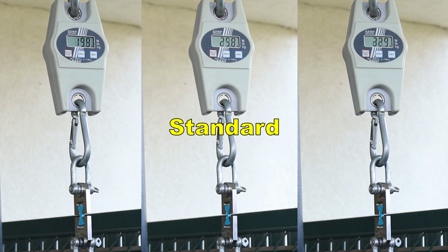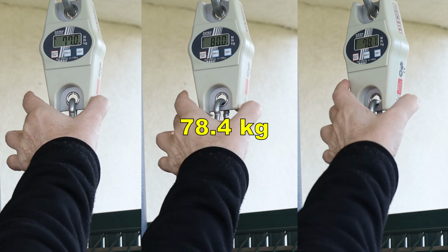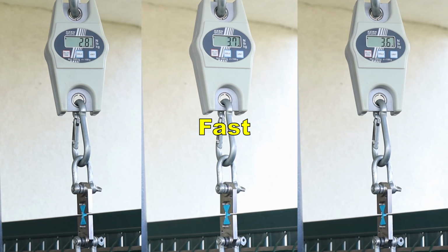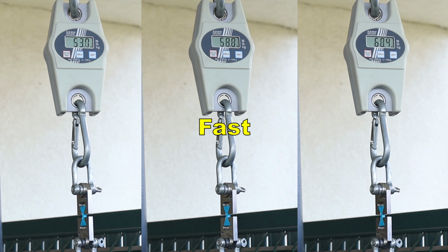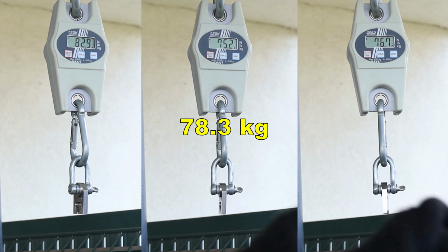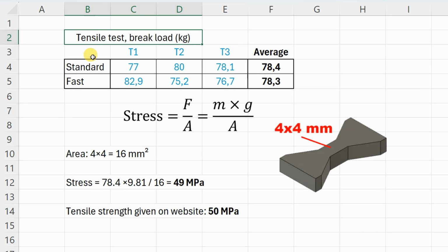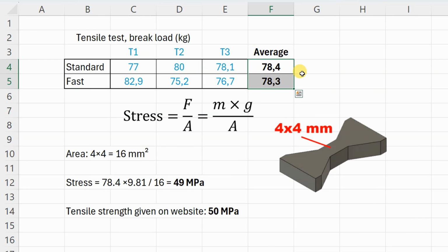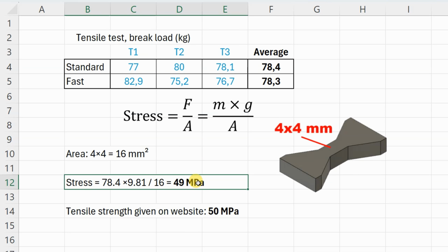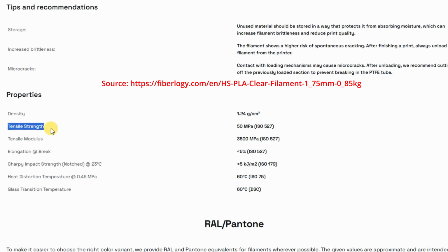Tensile test with horizontally printed objects, printed at standard speed, and printed at super high speed. This test is less sensitive to the settings, and I got very similar values. And if I calculate the stress from this, which is force divided by area, or mass multiplied by g divided by area, I will get that the stress is 49 megapascals calculated, which is very close to the value given on our website, which is 50 megapascals.